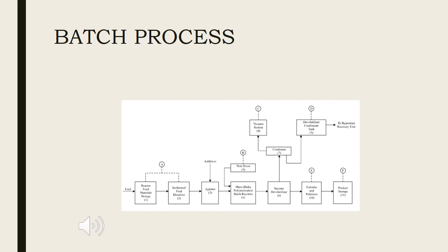It is a pre-polymerization reactor for mixing the reactants. A small amount of mineral oil as lubricant and plasticizer, the dimer of alpha methyl styrene as polymerization regulator, and an antioxidant are added.